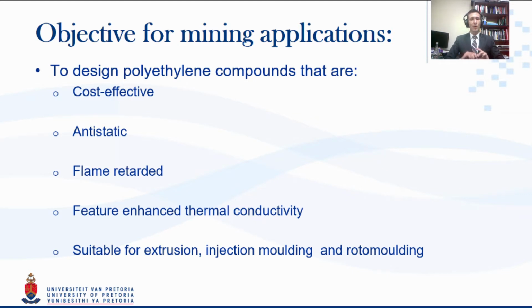So one of the very nice things about expandable graphite, and that is why we identified it to begin with, was that previous studies prior to the start of my studies at the University of Pretoria proved that there are anti-static and thermal conductivity abilities that can be achieved through the use of expanded or expandable graphite. Flame retardation, once again, is also one of its key facets.